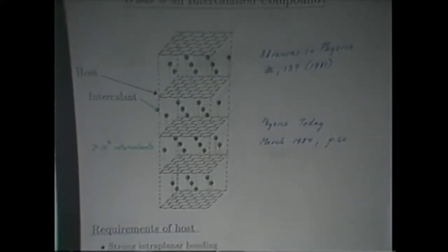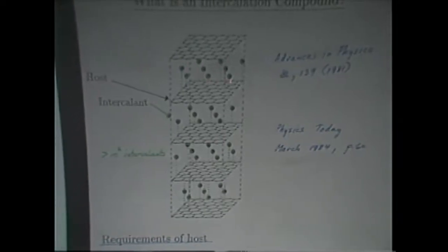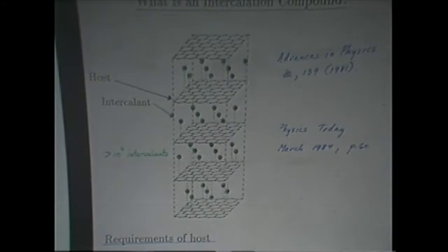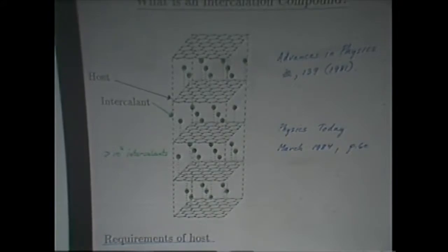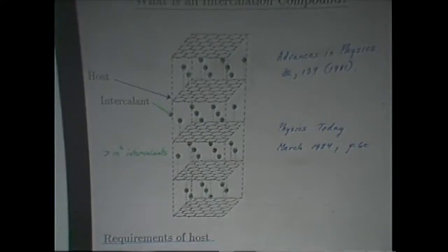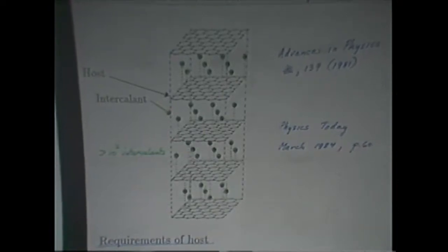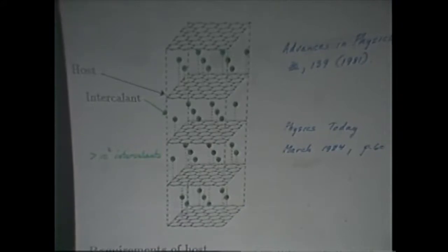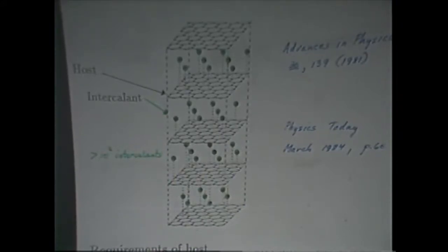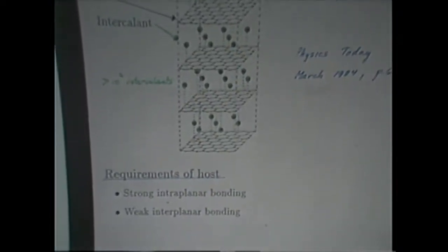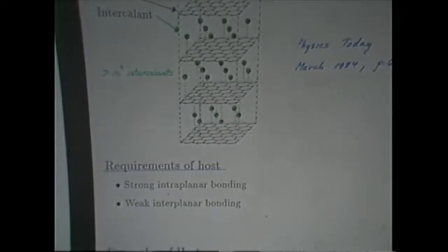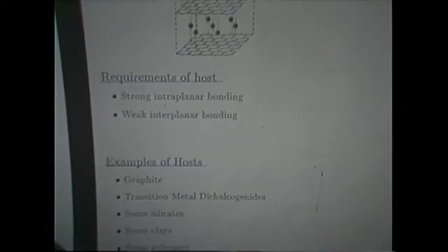So what is an intercalation compound anyway, and why do we care about them? Well, an intercalation compound is formed by the introduction of entire layers of guest species into a host material. Suppose the host material is graphite, as in our case here, and we introduce layers of some foreign species like an alkali metal. What are the requirements for this to happen? For one thing, it's necessary for the host material to have extremely strong bonding, so when the guest species is introduced, it doesn't mess up the layers of the host material, and of course that's satisfied in graphite. And the interplanar binding is very weak, so that it's easy to introduce whole layers of foreign species into the host material. Now, there are, in fact, a number of different host materials that will work. Graphite is only one of them.